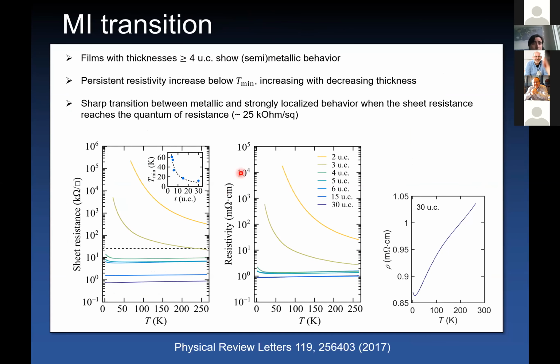All right. So thanks to all this material science and clean room work, we were able to study systematically the variation of transport properties as a function of thickness, and the result is reported here. Essentially, films that have a thickness larger than 4 unit cells show a semi-metallic behavior at all temperatures, and films that have a thickness of 3 unit cells and below show a sharp transition towards a strongly localized behavior.